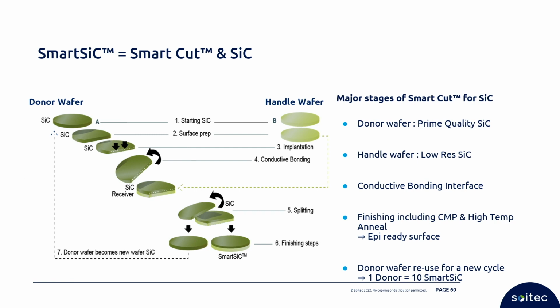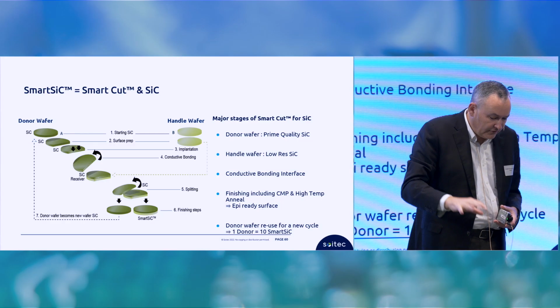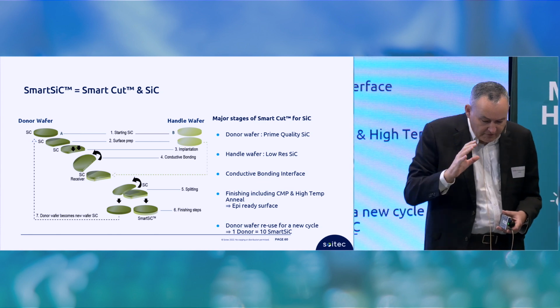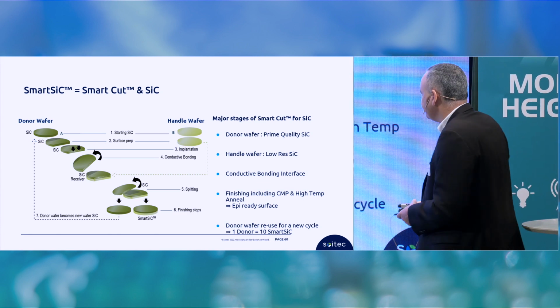When we apply it to SiC, what do we need? We need two wafers, one donor, one handle wafer. The donor wafer is a prime quality conventional mono SiC. The handle wafer, as I already mentioned, is a low resistivity poly SiC wafer. Surface preparation, Smart Cut implant, just to create a thin cleavage layer, and then conductive bonding. That's key. We will have a perfectly conductive bonding interface.